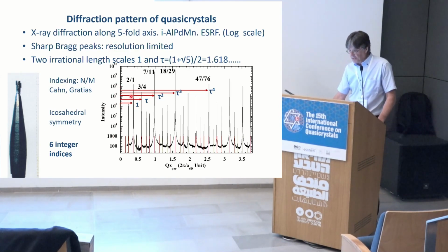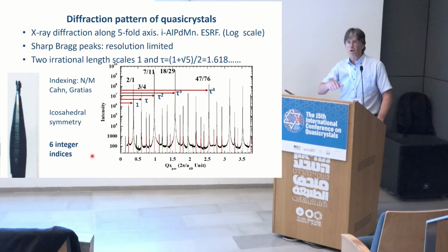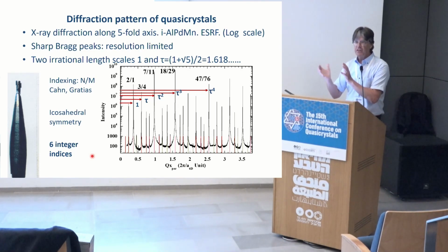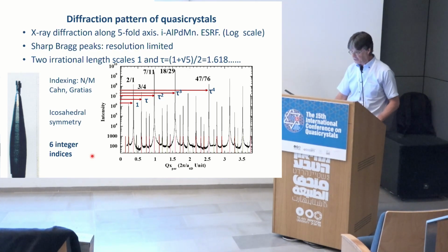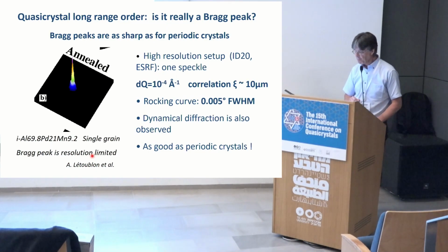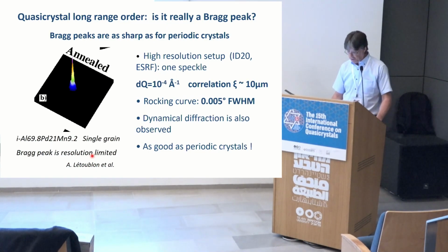We have again 1, tau, tau squared, tau to the power 3, tau to the power 4 scaling of the diffraction pattern. In principle, because it's icosahedral, now instead of 2 indices for 2D, I have to use 6 indices, and the periodicity is recovered in a 6-dimensional space. I'm using just a shorthand notation here. And to finish with the diffraction pattern,